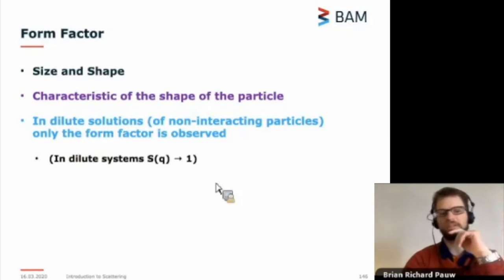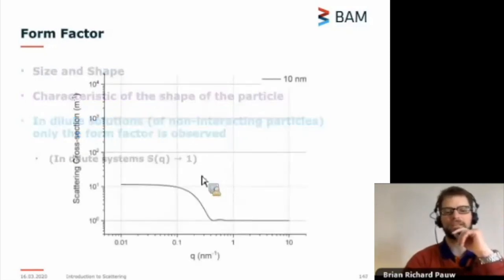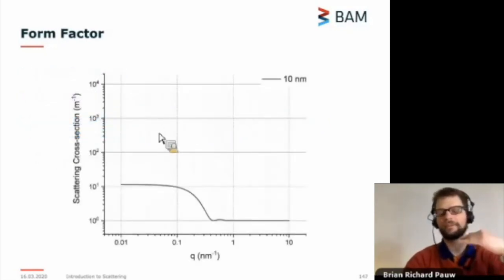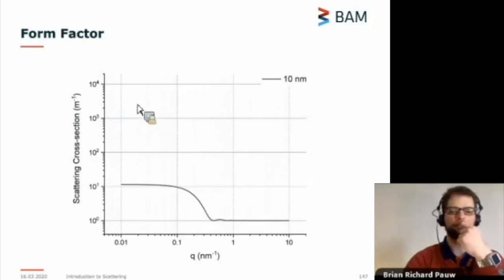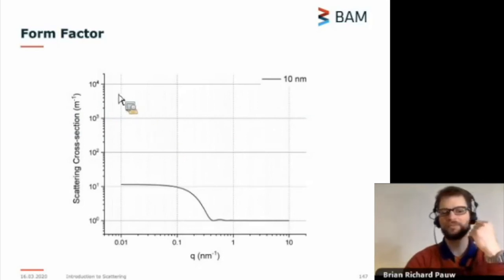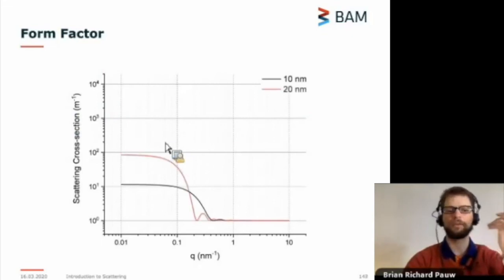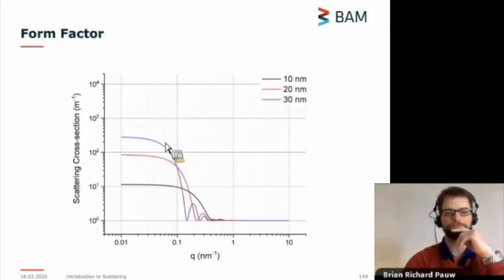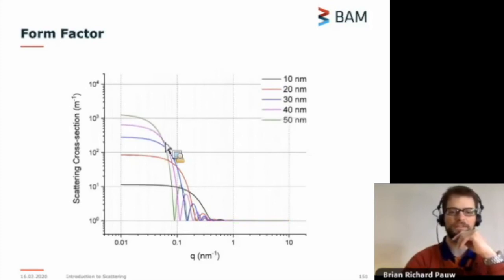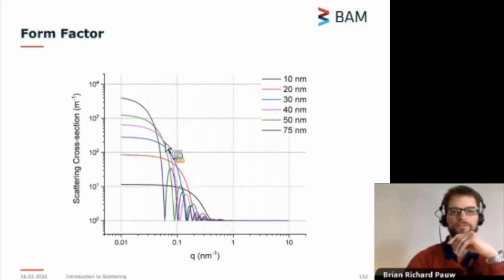It's dependent on the size because these form factors, I've shown here the form factor of a sphere with a background added, they shift to smaller angles the larger the structure gets. So if we have larger spheres, you'll get more scattering to smaller angles. But the interesting features over here, the characteristic feature of this size moves to smaller angles, and that's why you need to measure to smaller angles if you have larger structures.